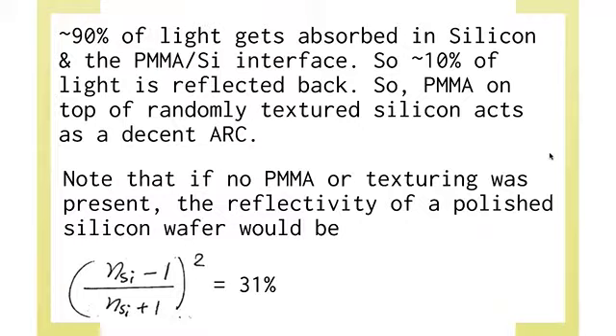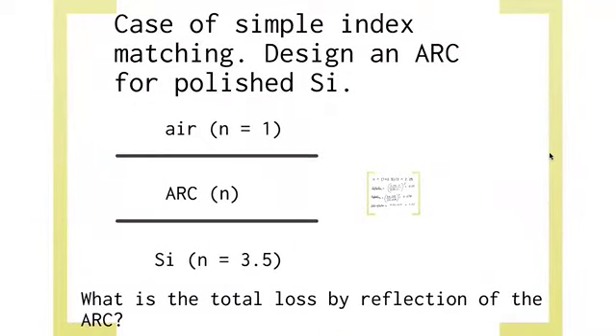ARC stands for anti-reflection coating. Note that if no PMMA or texturing was present, the reflectivity of a polished silicon wafer, which would look like a mirror, would be silicon minus air over silicon plus air, squared, about 31%. That's a huge loss, obviously. So the take-home message is that you want to make sure you have an anti-reflection coating in addition to the texturing, to ensure that as much light as possible enters the system.